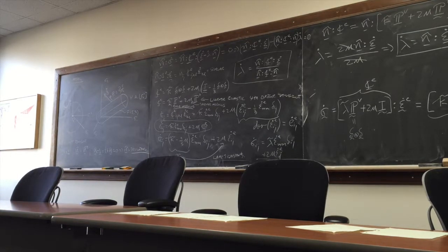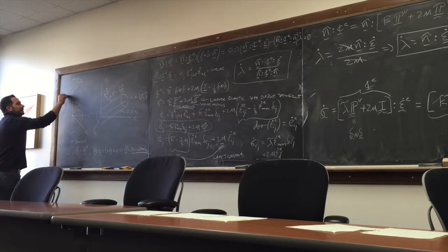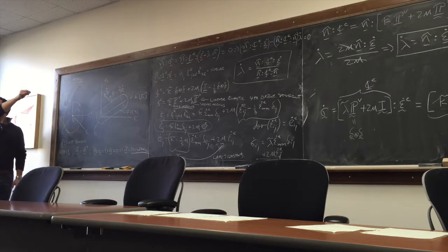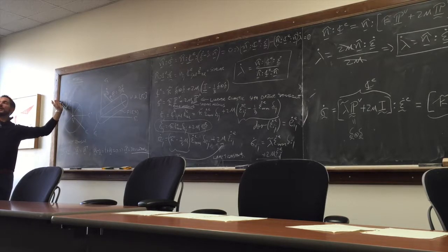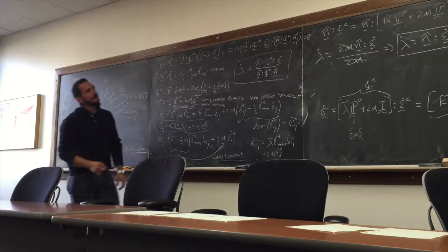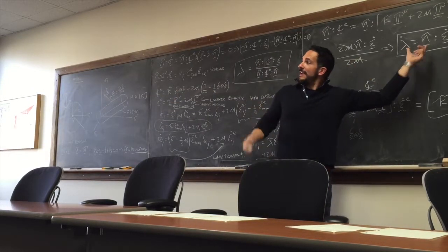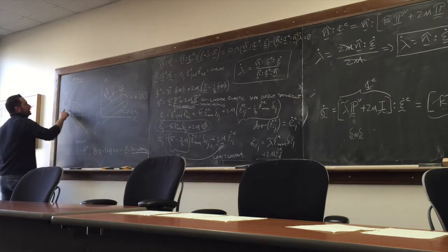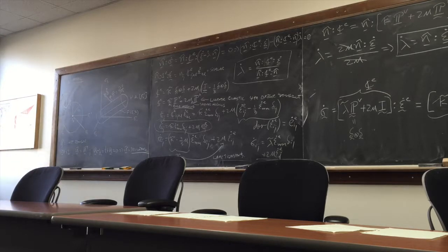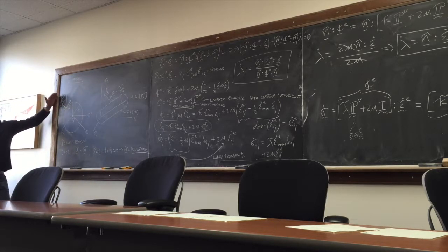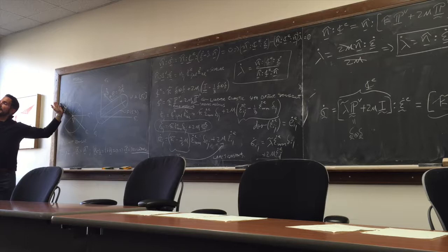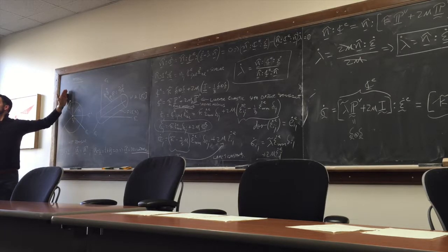See that? You have a strain increment that does whatever it wants. There's no restriction on epsilon dot. Then your plasticity says, wait a minute, you can't just do whatever you want. You have to be consistent. Epsilon dot will get a projection onto n hat, and that will give me the strength, the scalar value, the measure of plasticity. And then my plastic strain rate will be in the direction of n hat. Then, by the additive decomposition, you know that you have no other choice but for the other component to be the epsilon dot e component, right? So that when you add epsilon dot e plus epsilon dot p, you get epsilon dot. Okay, that's your additive decomposition.